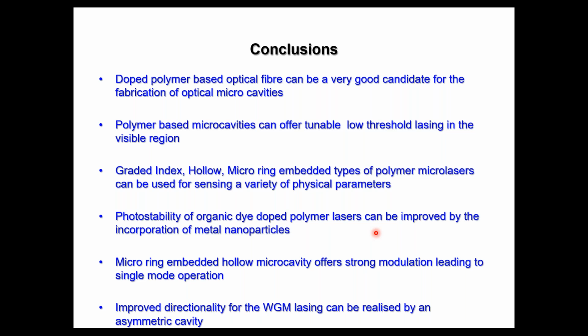Photostability of organic dye-doped polymer lasers can be improved by the incorporation of metal nanoparticles. Micro ring embedded hollow microcavity offers strong modulation leading to single mode operation. Improved directionality of the WGM lasing can be realized by an asymmetric cavity.